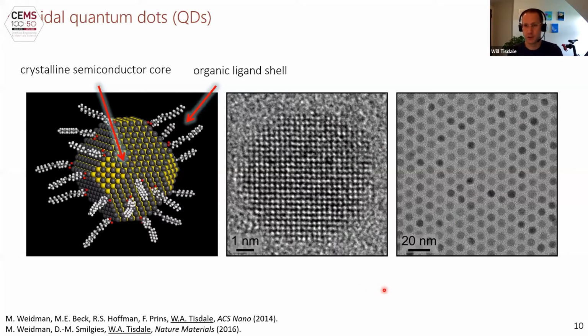If you've seen nanocrystals before, what you're supposed to be impressed by when you look at this image is the size and shape monodispersity. The synthetic techniques we use to make these materials have advanced to the point where we can synthesize gram and even kilogram scale batches of these materials where the standard deviation in the diameter is less than the size of the unit cell of the atom. So every nanocrystal in the batch is the same diameter plus or minus one layer of atoms on the surface. The empty space in between the nanocrystals is not actually empty space. That's the space that's occupied by these organic ligands that have much lower contrast in the electron microscope than the heavy lead atoms in the core.